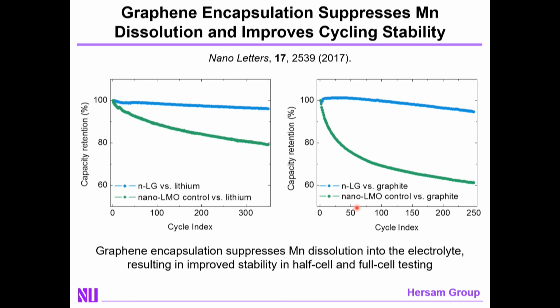It presents a physical barrier between the electrode and the electrolyte. It should mitigate unwanted chemistry between the two. In the case of lithium manganese oxide, that unwanted chemistry is manganese dissolution. And when manganese dissolves out of your cathode, you, of course, get a loss in capacity on the cathode side. But additionally, that manganese will find its way over to the anode, where it also causes problems on the anode side. So in a full cell battery where you use graphite as your anode, you see a very dramatic reduction in capacity upon cycling for lithium manganese oxide. This is why lithium manganese oxide is generally not used in commercial settings.